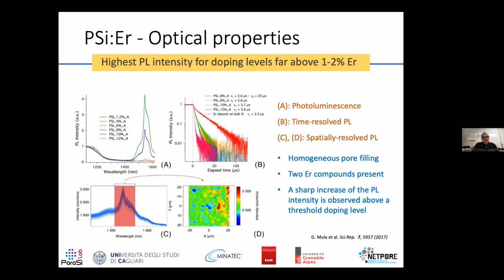A further check can be done to understand if this luminescence is regularly distributed along the sample. So this is a map measure of spatially resolved photoluminescence, where you can see that the emission intensity is regularly distributed toward the surface, not completely homogeneous, but this is normal also because when you fill tiny pores, it happens. It has been observed also with erbium filling. Sometimes some pore is empty or almost fully empty, just because of the chemical distribution of the material on the surface. But on the whole, you have a homogeneous distribution.